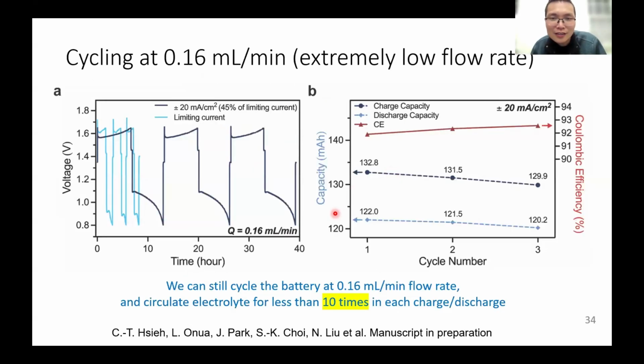And so that is the main finding of this paper. We also demonstrate here that even if you flow it at a very low rate, down to 0.16 milliliter per minute, you can still cycle it. And when you cycle it this way, your number of passes can be even lower than 10 passes in each charge discharge. Remember, people do hundreds of passes in the literature, and we are able to reduce it to less than 10 passes. And that significantly saves the pump energy.